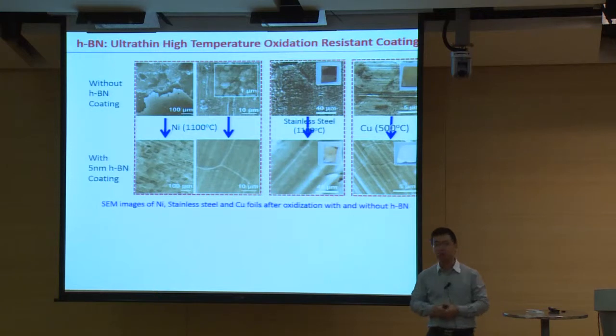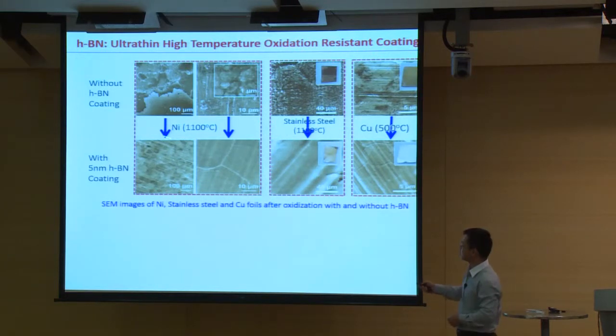And just like I mentioned, boron nitride is a material resistant to very harsh conditions like high temperature oxidation. So a very natural idea is, can we coat boron nitride on different surfaces as high performance anti-oxidation layers? So what we have done is we coat 5 nanometer boron nitride on different metal surfaces like nickel, stainless steel, copper. And then we oxidize them at a high temperature, such as for the nickel, we oxidize at 1100 degrees. Without the coating of boron nitride, what you can see is the surface of nickel has been destroyed, and there are a lot of nickel oxide grains. Okay, but surprisingly, with the coating of boron nitride, you can still see the texture, the grains of the nickel, and the whole surface has been preserved, protected very well.